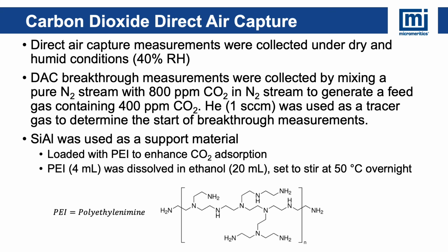Once again, we also introduced a small amount of helium as a tracer gas to determine the start of the breakthrough measurements. For our support material, we decided to use silica alumina, and we analyzed it both plain as well as loaded with PEI, where PEI is polyethylenimine. PEI is known for being a strong adsorbent for CO2 in the liquid phase, and we tried loading it into our materials by dissolving 4 milliliters of PEI in ethanol, and then we stirred it at 50 degrees C overnight and added our material in as well.